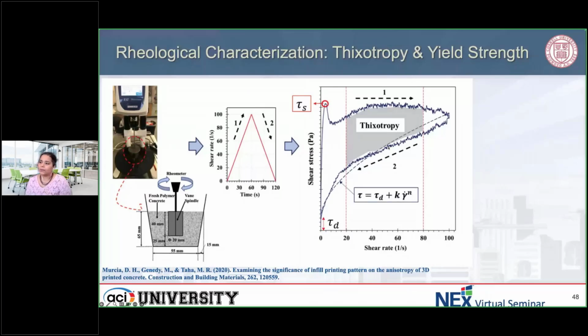The main thing that I want to mention with this test is that your material needs to be really flowable for you to be able to do this test. If your material is really stiff, like you're able to measure a good green strength, then that means that your vane inside will not be able to move, or even if it rotates, it just makes a hollow space. So you want to make sure that you're observing your material system as you're doing these tests. So you need to have a flowable mix to be able to do these tests.